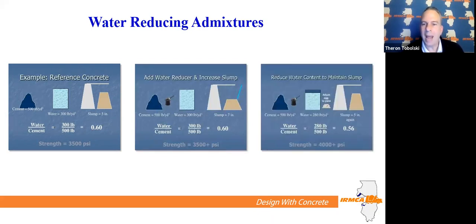We also could add that water reducer to that same mix, drop the water a little bit, so we would stay at that same 5-inch slump, but we'd actually be bringing the water cement ratio from a 0.6 to a 0.56, and we would actually create a 4,000 PSI mix. So we would be 500 PSI better than our previous two mixes. So it just kind of shows you the different ways water reducers can be used.